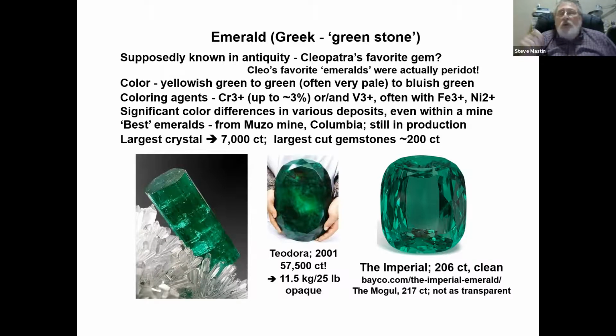And so if you look at an emerald through a loupe and you don't see that, it's either synthetic or the defects in it on the surface were filled in, sometimes with glass that's ground up and stuck into the cracks under pressure. All sorts of tricks, especially in places like Thailand, where lots and lots of gems come from.